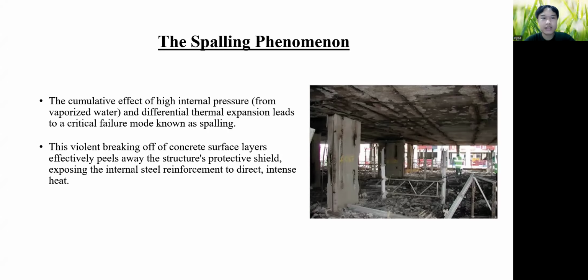The spalling phenomenon is basically a cumulative effect of high internal pressures from vaporized water. As I have presented before, from 100 degrees Celsius onwards, the water inside the members evaporates. So the differential expansion leads to a critical failure mode known as spalling. This violent breaking of the concrete surface layers effectively peels away the structure's protective shield. As the protective sheet is removed, the internal materials are exposed to the air and the failure happens.